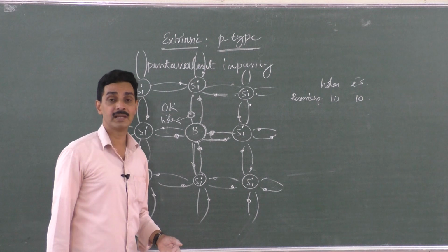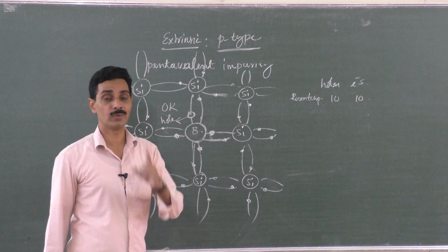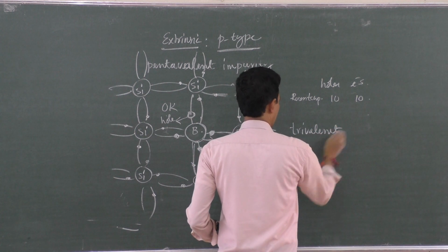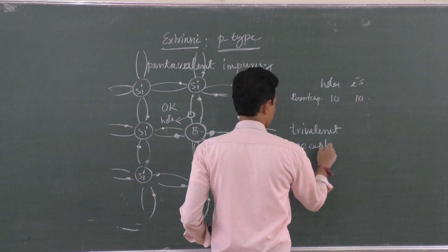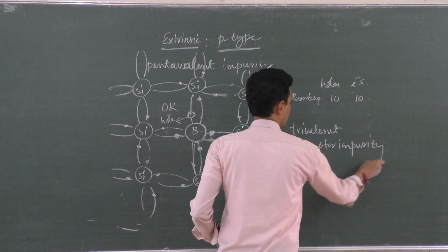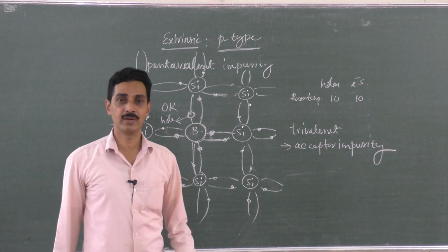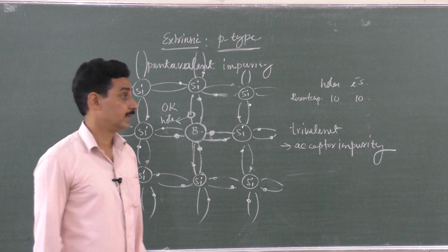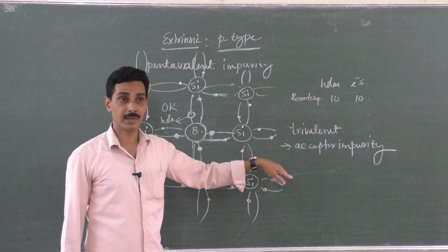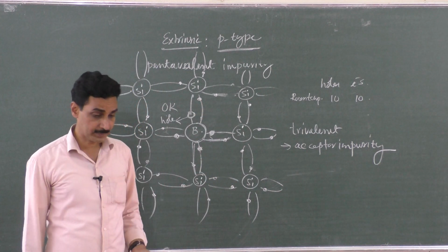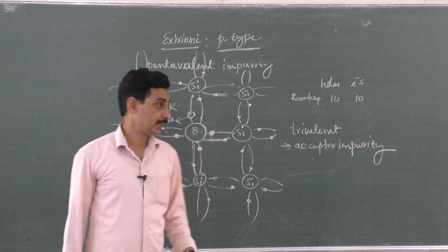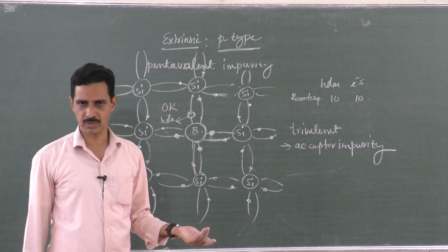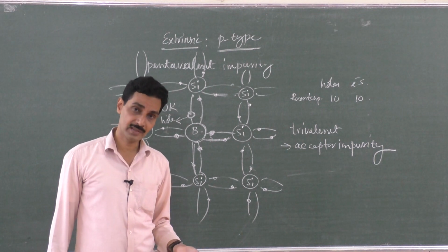And now, since each boron atom creates one hole, to complete all the bonds, it needs 1 electron. So boron or trivalent impurity is called acceptor impurity because it wants to accept one electron. Pentavalent impurity is called donor impurity because it can donate 1 electron free. This needs 1 electron to make the bond complete, so it is called acceptor impurity. So addition of acceptor impurity creates more and more holes, and now you get P-type semiconductor, because positive types of charge carriers are more, that's all. It is not positively charged. Again, P-type semiconductor is also neutral.